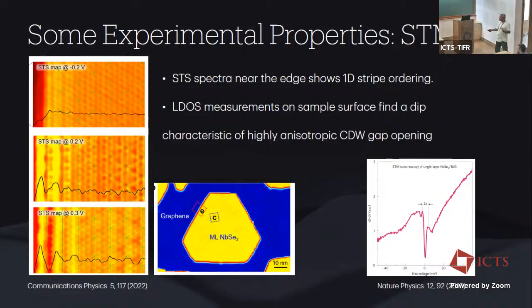However, they also found that if you look at the energy dependence of the STM features out here, it's not energy independent. If you go to, let's say, a very different energy scale, you recover back the 3Q order. It's only in an energy window that the stripe-like pattern is observed. So it depends on how you look at it, whether you look at it as a 1Q stripe order or essentially some energy dependent modulations.